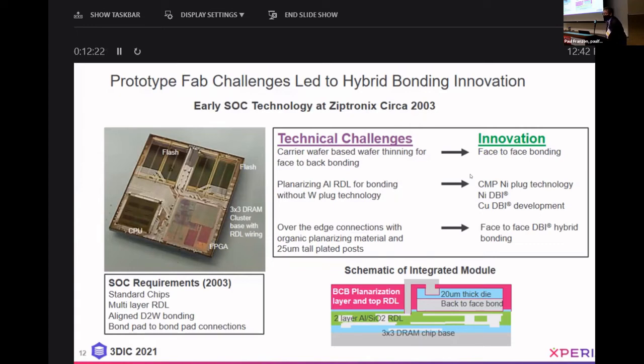The first hybrid bonding that we did was with nickel pads. And later, with CMP development of copper, we were able to develop copper DBI as well. And again, the over-the-edge connections with organic planarizing materials was very difficult, and this was much easier with face-to-face bonding with DBI hybrid bonding.